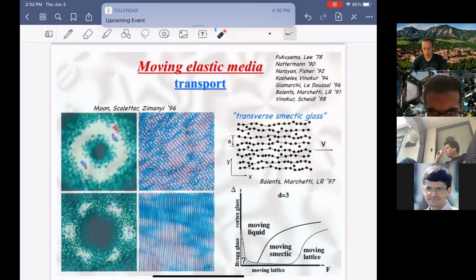And as a result, you can see here in the structure function, you get 2 Bragg peaks rather than 6 Bragg peaks. So at low velocity, you have 6 Bragg peaks, but at high velocities, you get 2 Bragg peaks. Namely, you've transitioned to this transverse smectic, and the whole picture is given in a cartoon way in this phase diagram. This is now a non-equilibrium phase diagram for a moving elastic medium that we use to understand vortices and other states of matter. Are there any questions?